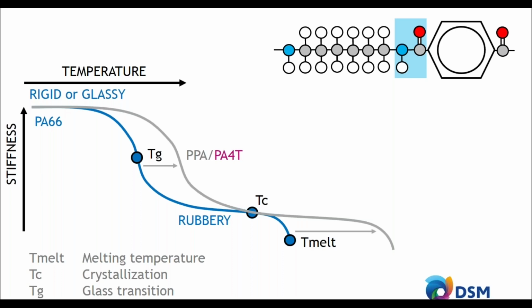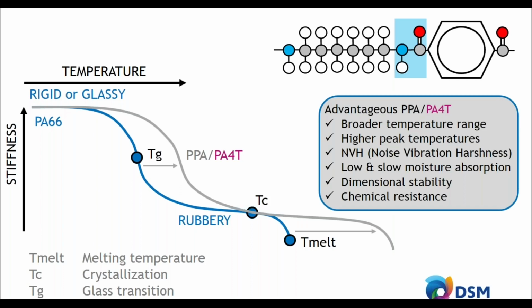Furthermore, you increase the melt temperature. It goes up to around 230, 240 degrees C, meaning that you can also accommodate much higher peak temperatures. So to summarize the advantages of a PPA over a polyamide 6,6: a broader temperature range due to the higher glass transition temperature, and higher peak temperatures due to the higher melt temperature. NVH could be improved because that is a combination of stiffness and damping, and all that stiffness is increased to a higher temperature range.